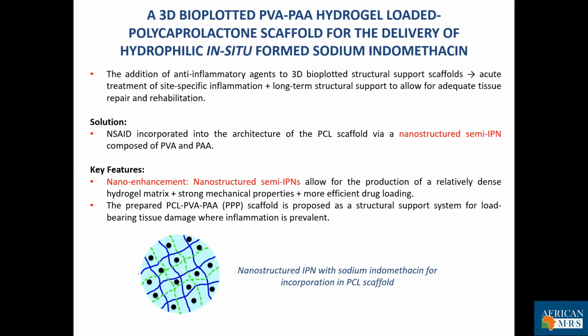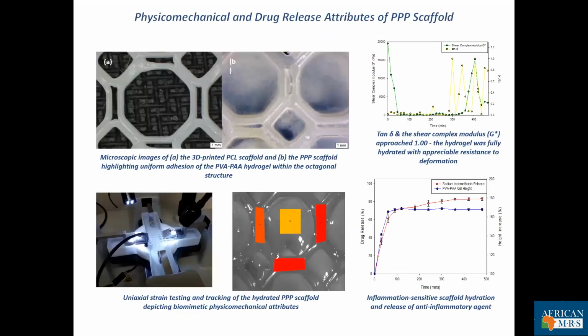So your nanostructured IPN allowed for the production of a dense hydrogel matrix that had strong mechanical properties and efficient drug loading. So here you can see some microscopic images of the actual matrices developed, and those were subjected to testing to determine the physico-mechanical properties, matching those with what is required inside the body. And we also saw that with hydration of the scaffold, there was inflammation-sensitive hydration with corresponding release of anti-inflammatory agents.